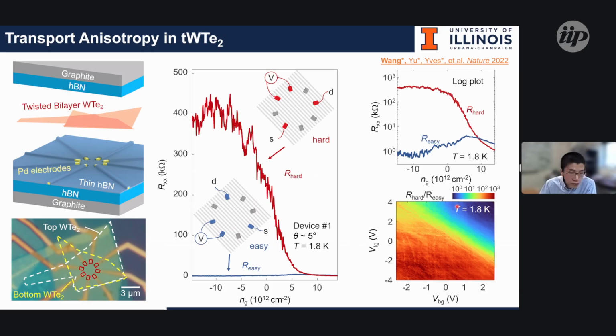We can further confirm this with dual gate tuning. You might have heard about dual gate tuning to tune the density as well as the electrical field during this workshop. On the left bottom side is where we have the most hole doping, and on the right top side is where we have the most electron doping. Crossing this tilted line is the displacement field direction. So you can see it's barely a displacement field effect, but mostly a density effect.